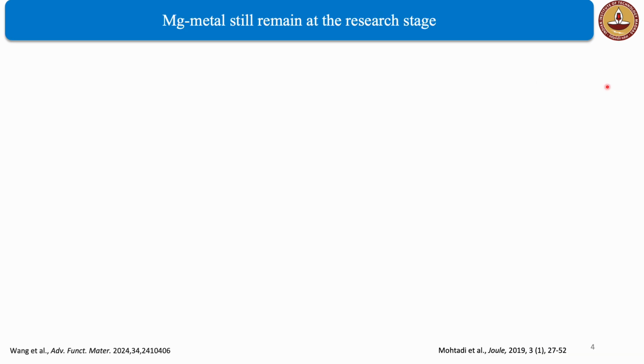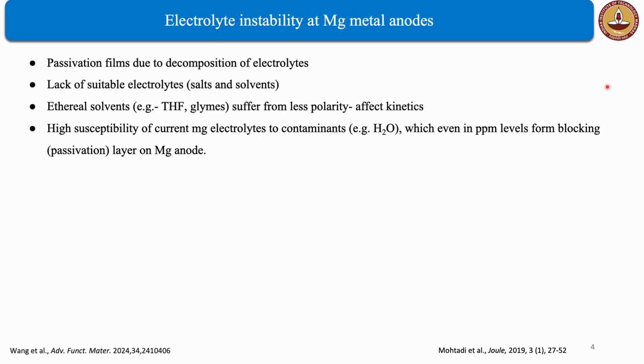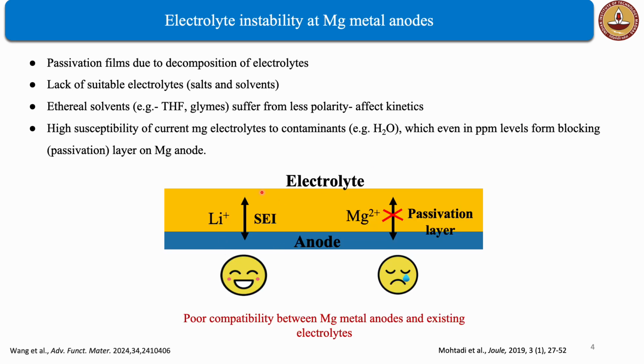Although the feasibility of magnesium-based electrochemical systems was demonstrated almost 3 decades ago, magnesium-ion batteries still remain at the research stage. One of the major issues in realizing commercial magnesium-ion batteries is the poor compatibility between magnesium metal anodes and the existing electrolytes. A wide variety of salts, solvents, and contaminants get easily reduced on magnesium metal anodes due to the low reduction potential of magnesium and form a passivation layer. Unlike lithium-ion batteries, where the SEI is conductive to lithium ions, this passivation layer does not allow the migration of magnesium ions, hence preventing the plating and stripping of magnesium.